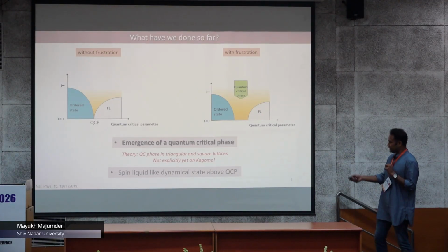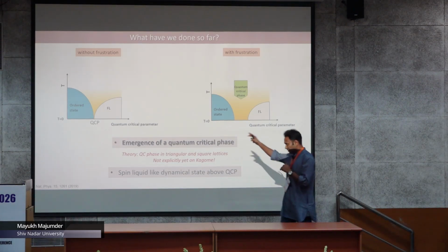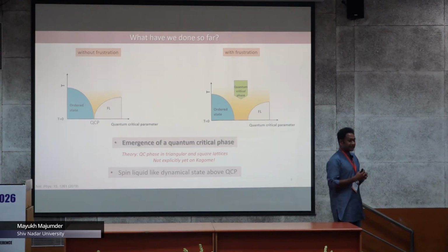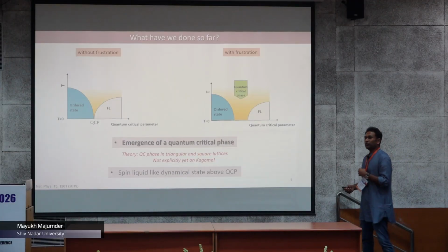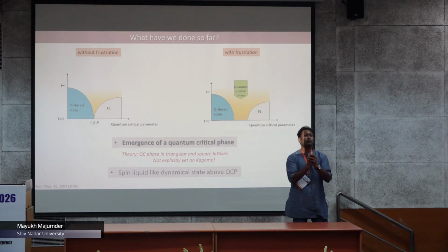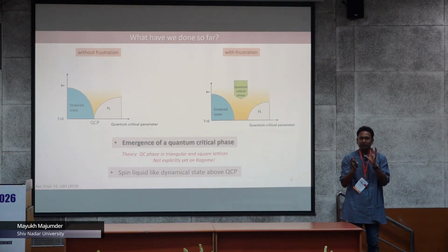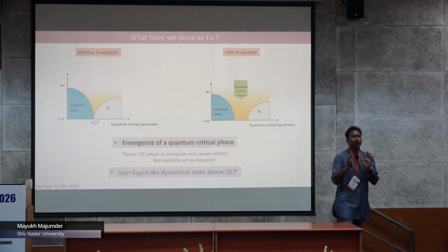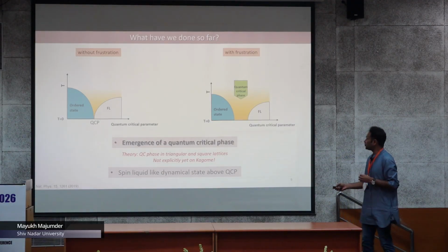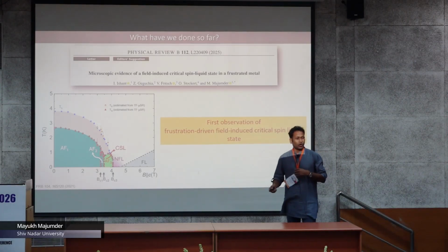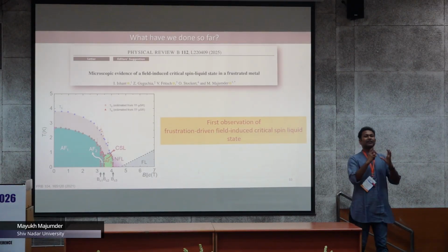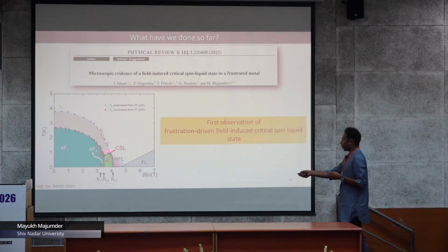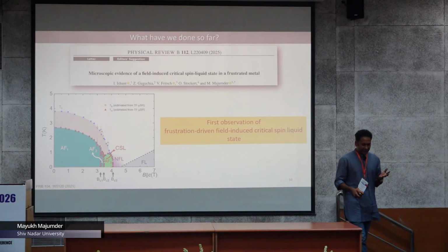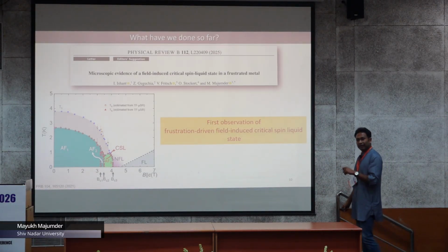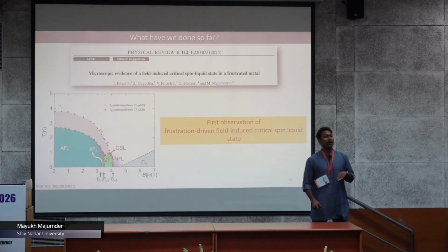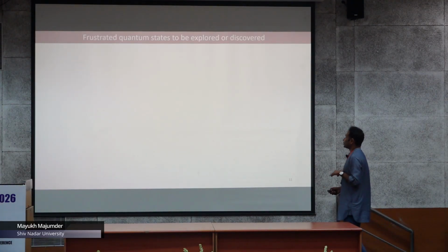Fine. Now you realize that the compound with which we did these experiments is a highly anisotropic material. While applying hydrostatic pressure on an anisotropic polycrystalline material, things get complicated, right? You do not know whether what you are saying is truly correct or not. In order to avoid that, we also applied an external magnetic field on a single crystal of the same compound, and we saw that there is also a critical spin liquid-like state driven by the external magnetic field if you apply the field along the Kagome plane. So far so good.